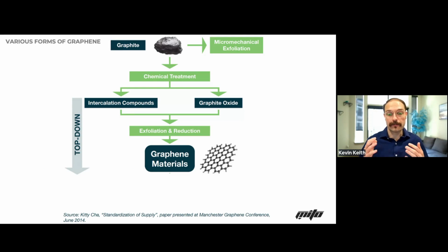So in order to make a graphene, there's a couple of different ways you can do this. One is called a top-down method. Top-down is when you take graphite, so think pure carbon, 85 to 99.9% carbon, depending on what your feedstock is, and you're able to do a couple of different things with this. You can do mechanical exfoliation, where people send it through a grinder. You can do mass amounts of this, but you're still making graphite. Graphene nanoplatelets, if you will. It's smaller chunks, but you can't control the morphology, the layer counts, the defects. You're just regrinding it up into a powder.